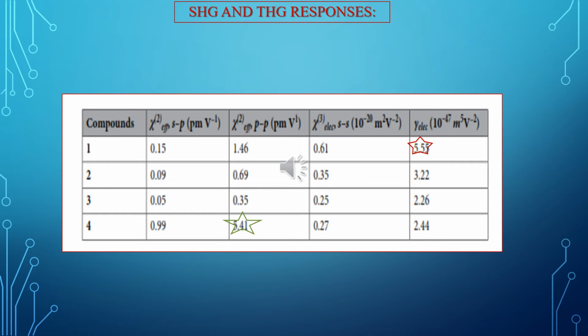The complex 1 is characterized with a higher third order than 2, 3, and 4 due to more effective electronic delocalization, which is caused by charge transfer from the N,N-dibutylamine and ferrocenyl donor groups to the azo-accepting unit. These results indicate that the present organometallic complexes are valuable candidates for optoelectronic and photonic application.